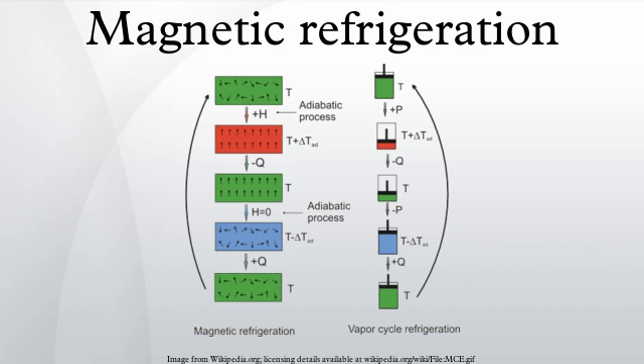Currently, alloys of gadolinium producing 3 to 4 Kelvin per Tesla of change in a magnetic field can be used for magnetic refrigeration. Recent research on materials that exhibit a giant entropy change showed that Gd5Si(1+x)Ge(4-x), LaFe(1+x)Si(13-x), and MnFeP(1-x)As alloys,